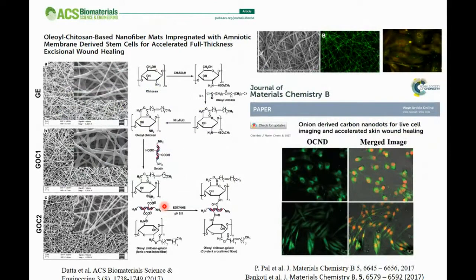And of course, we have used different biopolymers like chitosan from crab shell or shrimp shell. And these chitosan nanofibers were fabricated by modification with oleoyl chitosan. And these kind of polymers, simply because of amphiphilicity, you can do phase separation and you get the nanofibers. And these nanofibers were mixed with the carbon dots having fluorescent properties. And when these carbon dot loaded nanofibers are grafted on the skin side, right?